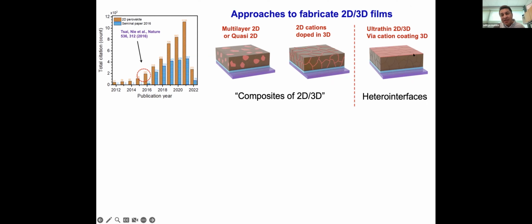And the idea here is that you take an organic cation and then you spin coat the organic cation on a 3D perovskite film. And when you do that, this organic cation steals some of the lead iodide from your bulk film and forms a passivation layer, a very, very thin layer of 2D perovskite on top of this 3D film. Now, what you cannot control is the N value in this case.